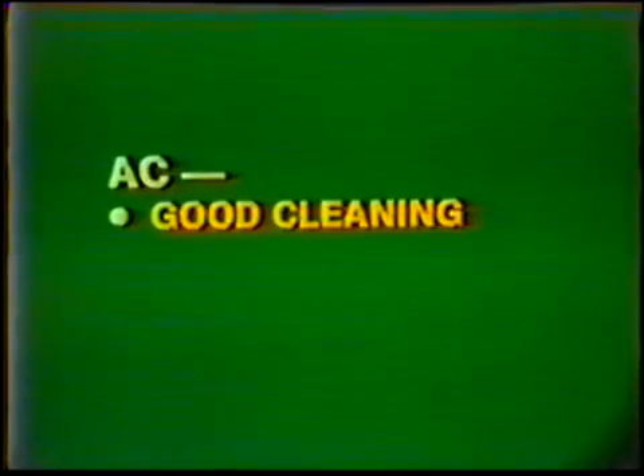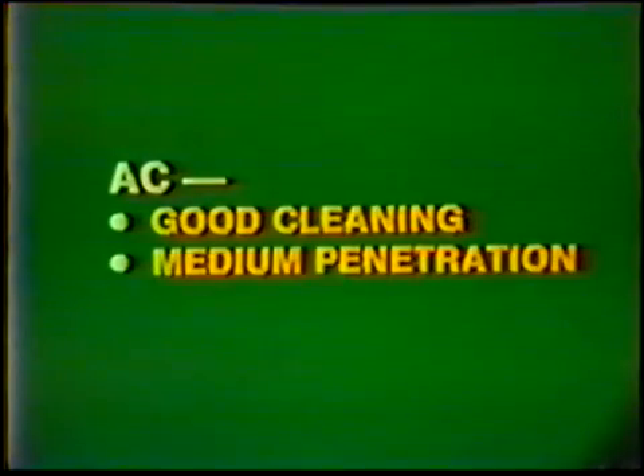Alternating current possesses good qualities of both direct current electrode positive and electrode negative when welding metals with a relatively thick oxide coating, such as aluminum or magnesium. During the electrode positive portion, the current breaks down the surface oxide of the base metal, while the electrode negative portion of AC produces medium penetration. Alternating current provides good cleaning action and medium penetration, which makes it ideal for aluminum and magnesium.